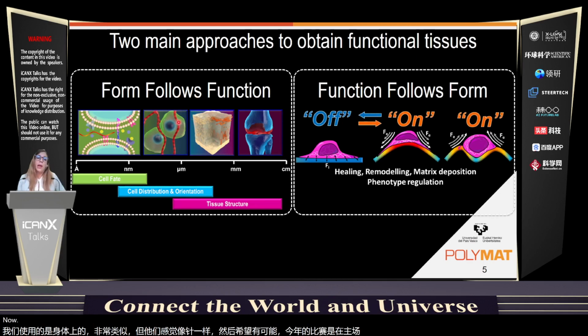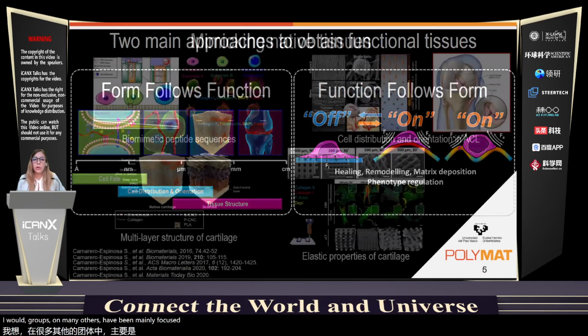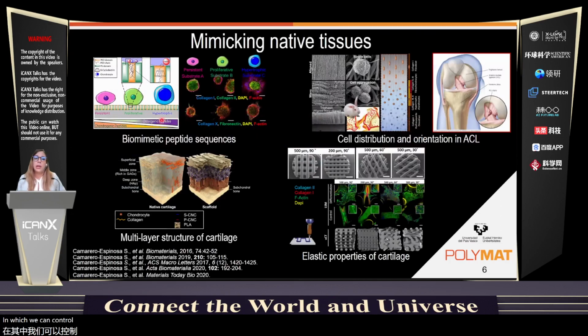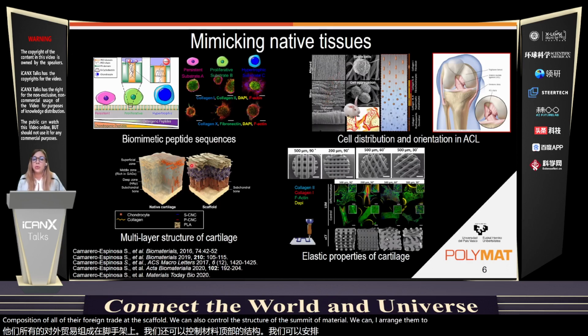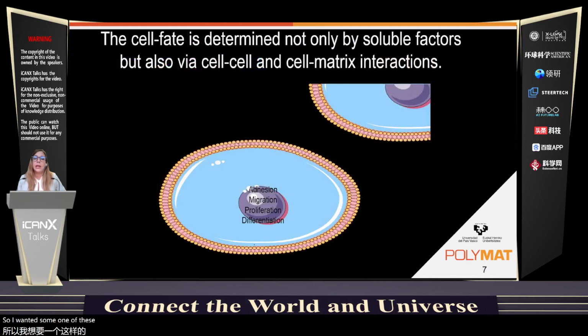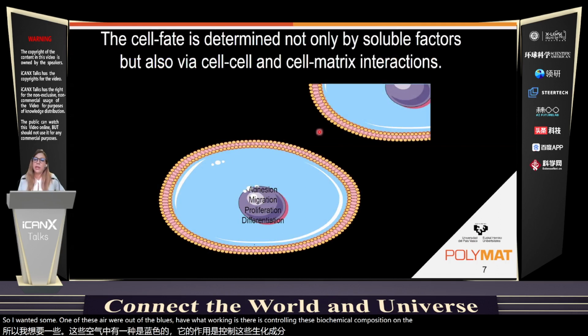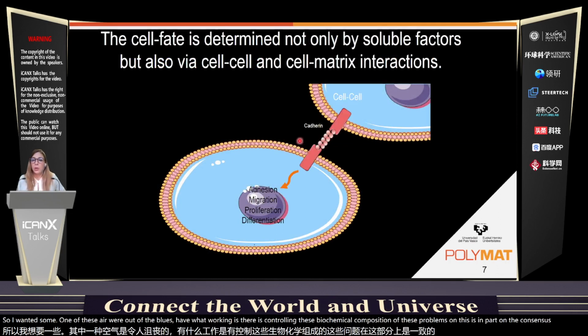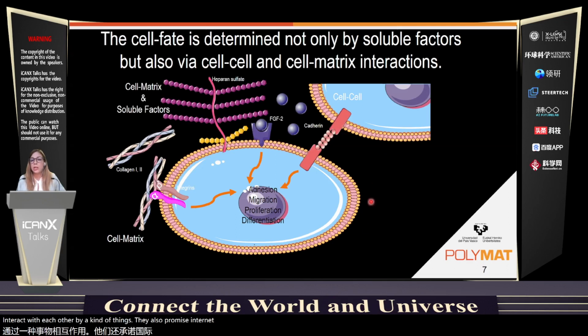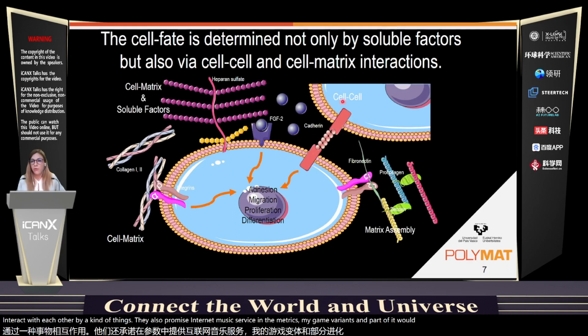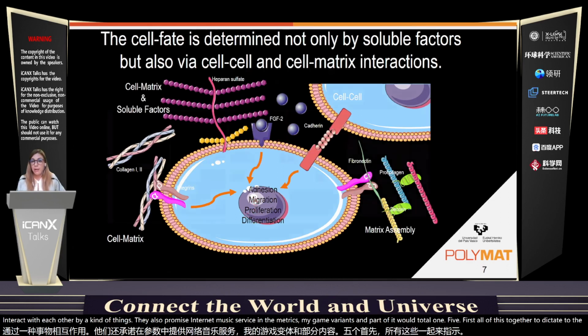Now, our group and many others have been mainly focused on this first approach, in which we can control the chemistry and the biochemical composition of the fabricated scaffolds. We can also control the structure of the fibrous material. We can arrange them into multi-layer scaffolds and further control the mechanical properties. So one example of this, where a lot of groups have been working, is controlling this biochemical composition of the scaffolds. And this is important because cells interact with each other via cadherins. They also can interact with the extracellular matrix via integrins and further with soluble factors. All of this together dictates the cell fate.